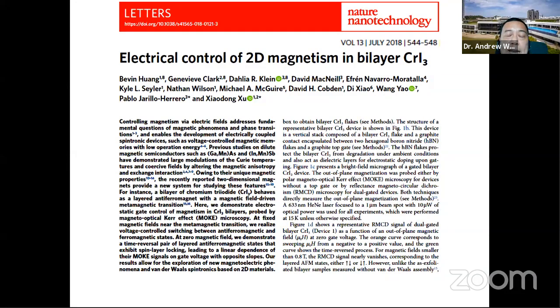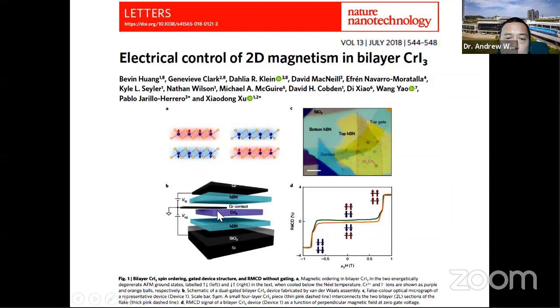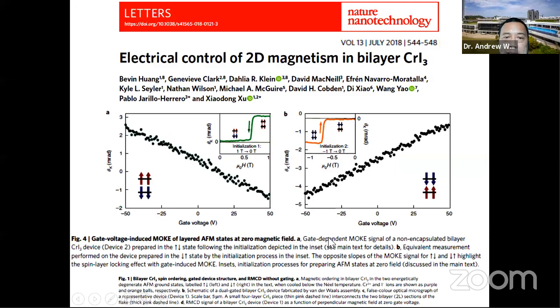Okay. So I mentioned chromium iodide. People are excited over this material because bilayer chromium iodide is found to be anti-ferromagnetic, and as shown 2 years ago by Xiaodong Xu's group, it is possible to electrically control the 2D magnetism. In this configuration where the chromium iodide is sandwiched between electrodes, you can see a curve where at zero field there are these degenerate anti-ferromagnetic states, and at high positive or negative fields, you get flipping to ferromagnetic states. They have also shown it's possible to use the gate voltage to control this flipping between ferromagnetic and anti-ferromagnetic states.